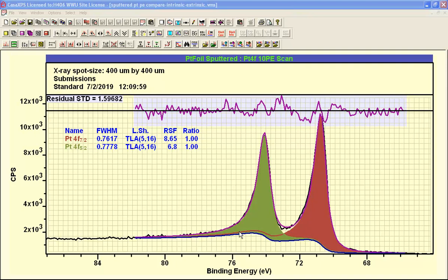However, once you introduce asymmetry, that may not be the case. While the functional form for a background may integrate to infinity quite happily, in the case of a photoemission peak, we should be able to calculate an intensity that we can use in quantification. An infinite area line shape is of little value when quantifying data by XPS.